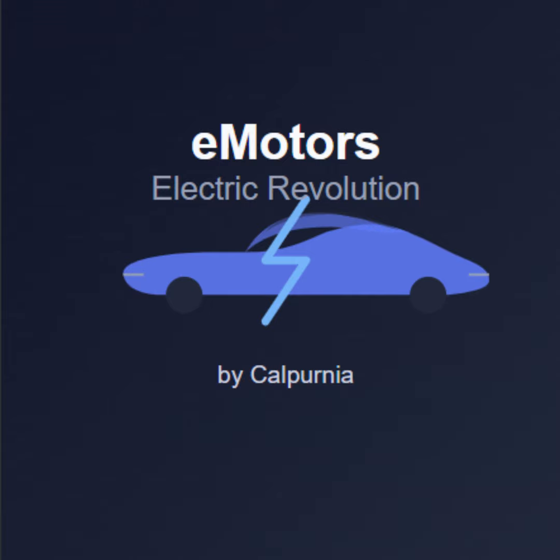The sources often highlight the original Chevrolet Volt plug-in hybrid as a classic case study. It was well known in engineering circles for having very large top and bottom buffers on its battery pack compared to many other EVs of its time. And the result? Data showed the Volt's battery exhibited slower than average degradation over its lifespan. It clearly demonstrated the long-term benefit of sacrificing a bit of usable range up front for that maximum protection, especially from those high SOC levels. Interesting.